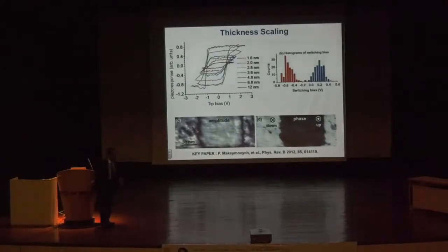Okay, what we've been doing over the last year or so is to understand how the order parameter changes, how the switching of the ferroelectric crystal changes as I reduce dimensions. This is work we did a few years ago, actually, using piezo force microscopy. We know that even 2 unit cells of bismuth iron oxide is a good ferroelectric. It is not the same ferroelectric. It suppresses its order parameter quite a bit, but it's definitely switching.